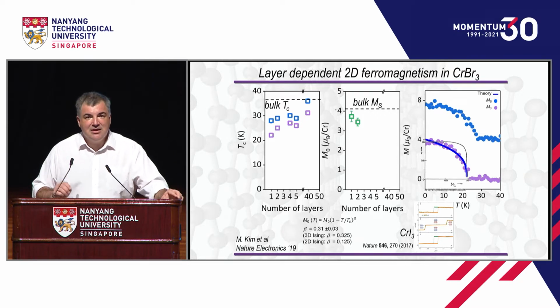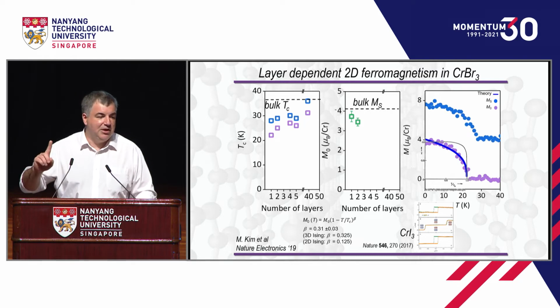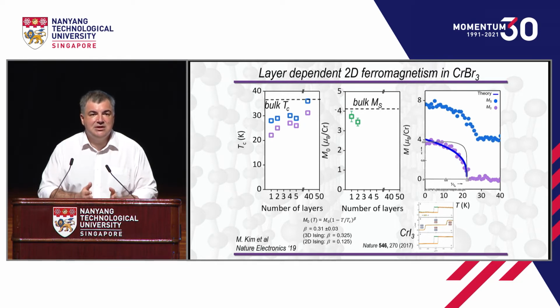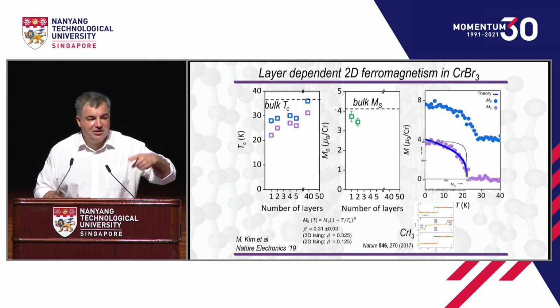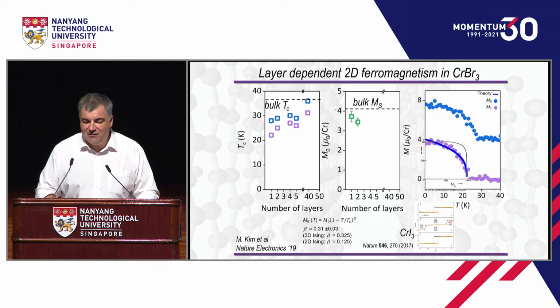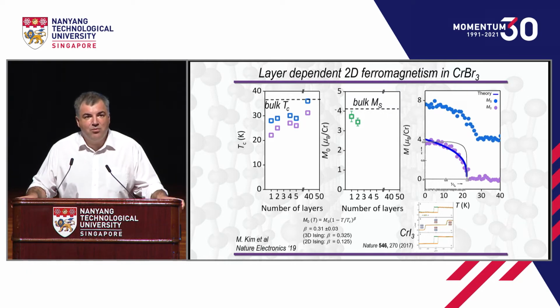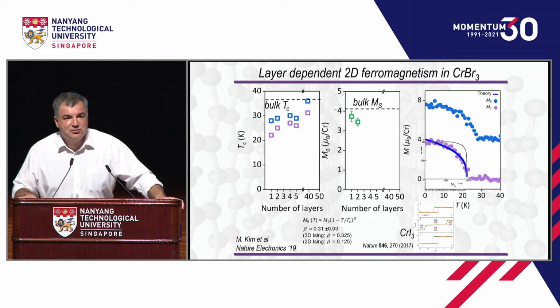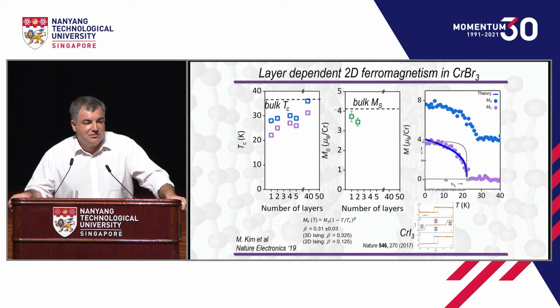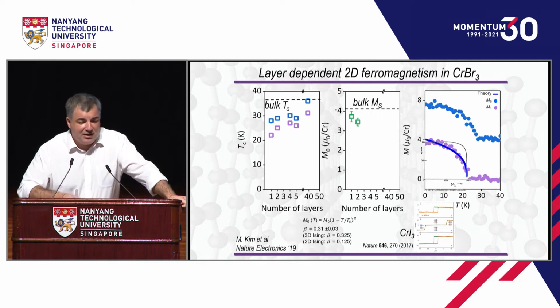And that's the phenomenon which I was telling you before, that in two-dimensional crystals the situation becomes much more interesting. So spins are not purely spin up or down like in Ising models. Of course, Lee and Yang assumed the Ising model in his calculation, hence that very sharp behavior. So in our case, in real materials, you have some more complex behavior, maybe something which was introduced fairly recently by Kitaev. So we have some other behavior, and that's why it's really exciting to compare our results with the exact predictions of the simple Ising model.